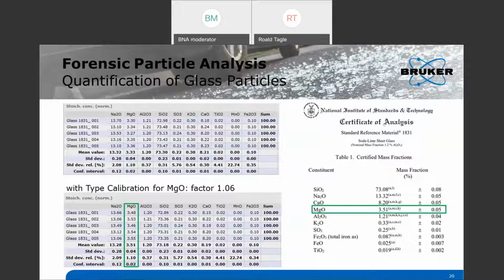The M4 Tornado comes with a fundamental parameter quantification. That means you don't require reference materials to quantify a sample. You see, for example, the results of the analysis of the reference material NIST 1831. You see the results at the top, and if you compare that to the expected values, we see, for example, that the magnesium values are a little bit lower than expected.